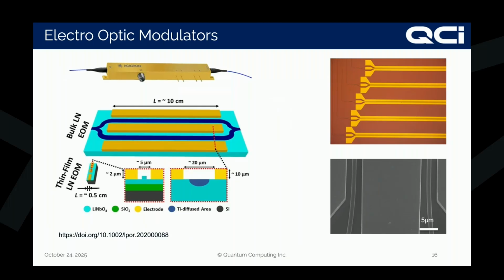So what happens in that case is that the confinement of the field is spread over a wider area. Therefore you have less control over how you can manipulate the light that is going through it. But in the thin film version, you can reduce the spacing to 5 micron and reduce the electrode thickness to as low as 2 micron or even lower. And that gives you better confinement and better control of the electric field inside the material in thin film lithium niobate, and that gives you better control over the modulation of light through the electro-optic effect.